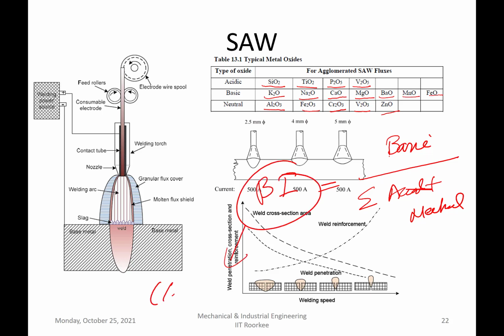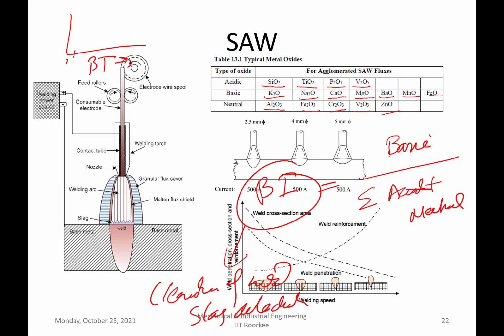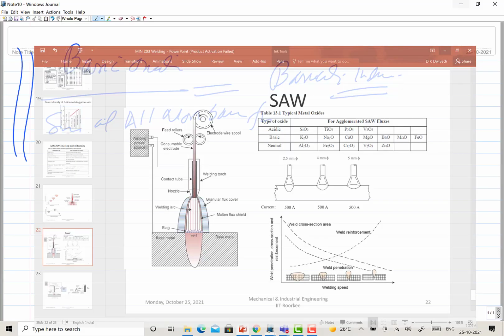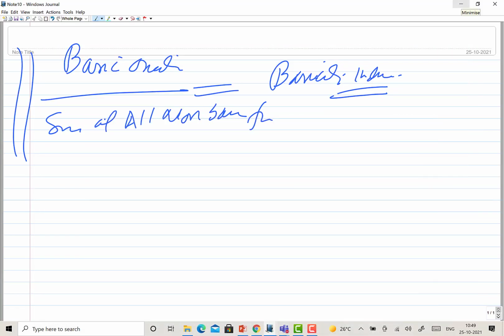Basicity index directly affects the cleanliness of the weld, number one, and number two, it also affects the slag detachability. So it's important. If you write BI here, basicity index, let's say 1 to 5, then you will find that the oxygen content in the weld is coming down with the increasing basicity index. So O2 content in the weld is reduced with the increasing basicity index. That's why I said that it affects the cleanliness of the weld. So in submerged arc welding, basicity of the fluxes is quantified using a simple formula: the weight percentage of all basic fluxes divided by all non-basic fluxes.